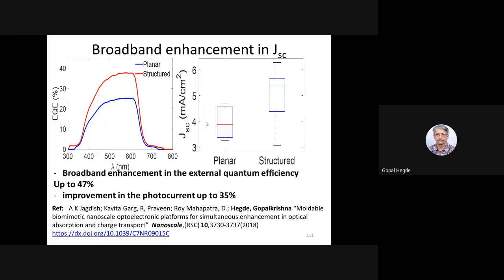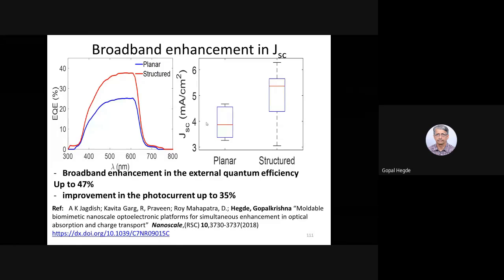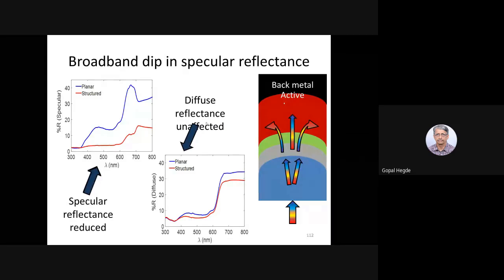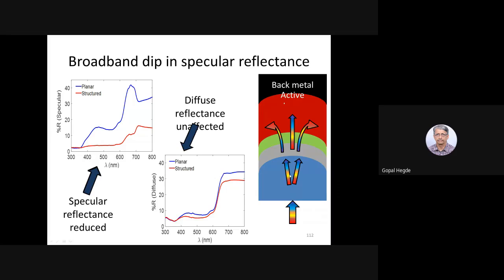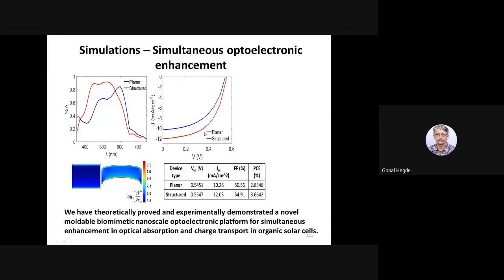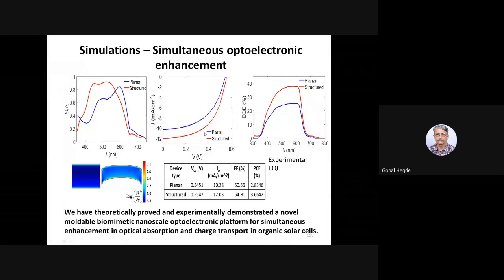Okay. So this is what we observed by introducing nanophotonics in photovoltaics. We observed a very good enhancement in efficiency, photocurrent, and minimum reflection. You can see a broadband dip in specular reflection, and you can see how broadband light is going into a nanostructured photovoltaic cell, and each of these photons is coming back within the structure. There is minimum loss, and you can see specular reflection is minimum in the structured one, while diffuse reflectance is higher. Whatever we saw in the model simulation, almost all was realized in the real experiment, and I think we have a patent for this one as well. And all this is possible with nanophotonics.